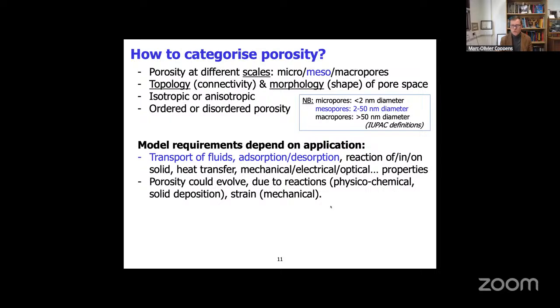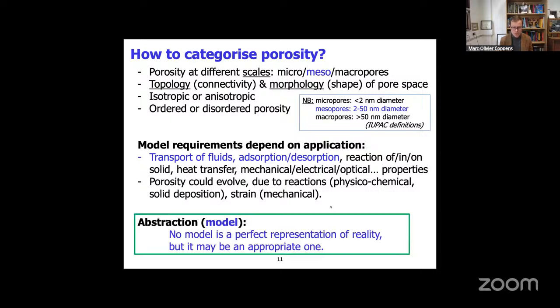So the porosity also, if we have reactions that are involved, could evolve. For example, due to catalyst deactivation with coke that is depositing in the pores, or you have mechanical transformation due to heat. You may have strain and mechanical aspects that become important so that the pore shape, size, the material properties really change, and that affects also the porosity. Then it becomes much more complex. So as you see, I'm trying to give you a bit of context for models. And so what is then a good model, right?